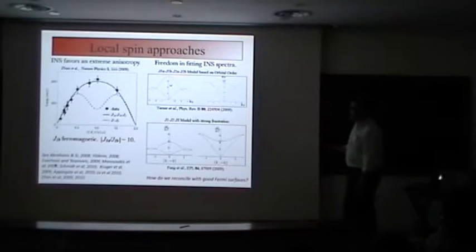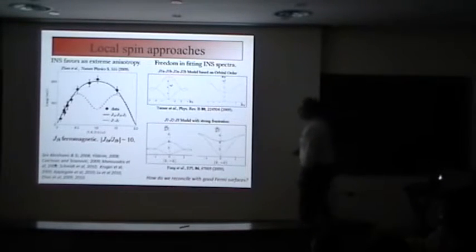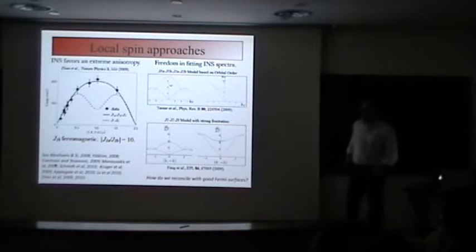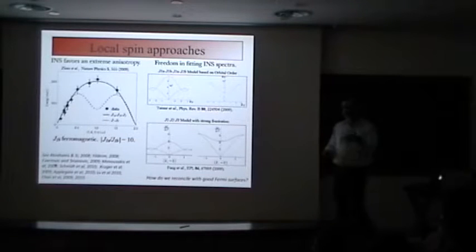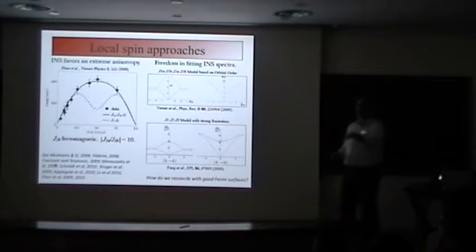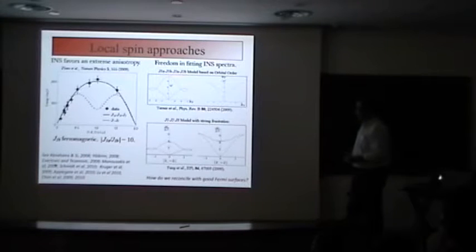Or J1, J2, J3—another model with strong frustration—again producing dispersions quite similar in both cases. So it's not enough to just look at the neutron spectrum and its dispersion alone; one should look at the intensities and understand the spectral weight and dispersion over the entire zone. I think this gives a good way to think about things, but of course it doesn't capture the fact that we have good Fermi surfaces.